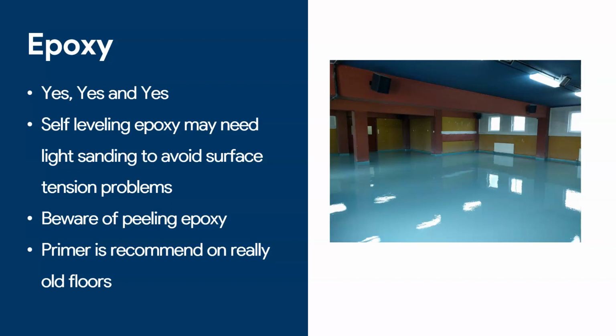If you have a very smooth self-leveling surface like this one here, I would always recommend that you lightly sand the surface or you prime it in advance, because you may have some surface tension problems. If the surface is really glossy, the new coat on top may have problems leveling out properly. I have had problems with craters in the past where we applied a fresh layer of epoxy over an old very smooth and glossy surface and we got craters.